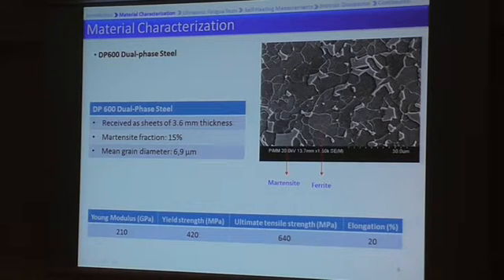The material under study is the dual-phase steel. As you can see, its microstructure is in this picture. It consists of hard martensite islands dispersed in a soft ferritic matrix, and you can see the mechanical properties of the material in this table. It was received as sheets of 3.6 millimeter thickness, and it contains 15% of martensite.